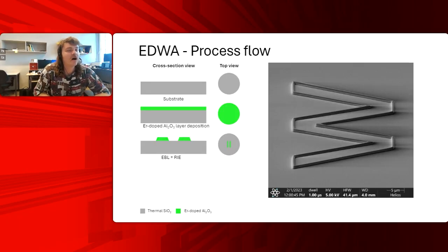After we are happy with the films, we'll move on to electron beam lithography, which we use to designate the resist etch masks, which would be simply a resist that is electron beam sensitive. And using reactive ion etching, a dry etching technique, we can define these very straight, somewhat angled, but straight enough waveguide sidewalls. You can see there a nice W being patterned and SEM'd in our erbium-doped aluminum oxide.